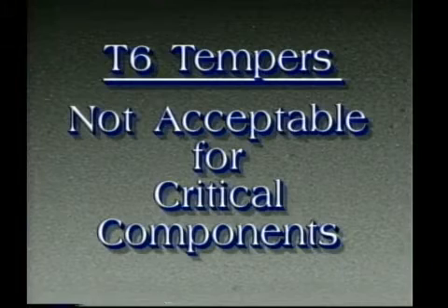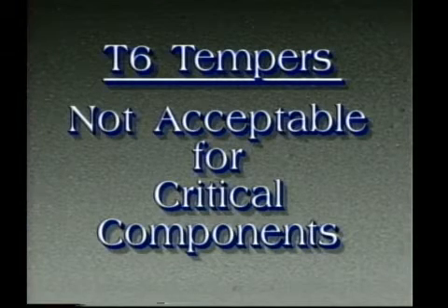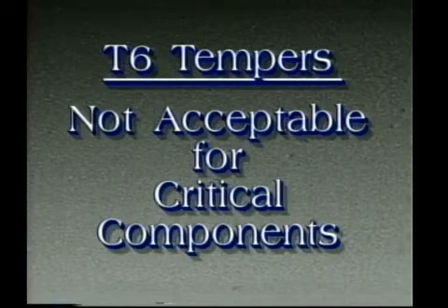In service, a part aged to the T6 temper may satisfactorily carry the required ultimate load for a short duration. However, if the same part is exposed to a mild corrosive environment and either contains a high level of residual stress or is subjected to a continuous load, premature failure can result. Thus, in order to make these materials more usable, it is necessary to overage them to lower strength levels in order to achieve better resistance to corrosive environments.